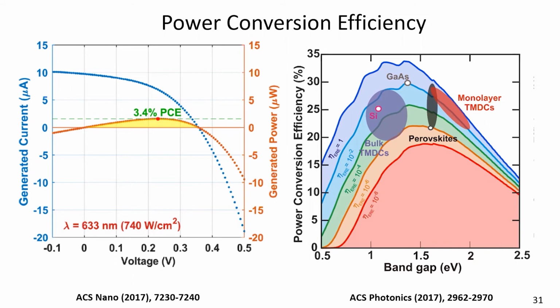Now the real question is, where do we stand in terms of power conversion efficiency, and how far can you go? We stand right here, somewhere below 5%. But if you look at the detailed balance model and try to do a calculation of where bulk TMDCs should lie, and I'm saying bulk TMDCs because all of our cells are few layers in thickness, which is essentially electronic bulk, and you look at their band gaps and compare them, they should be very close to silicon. But they are not there. They are somewhere below 5% over here. And so where are all these losses going?